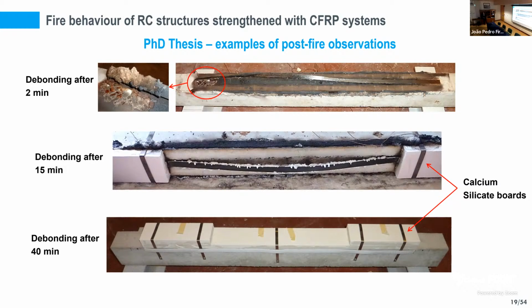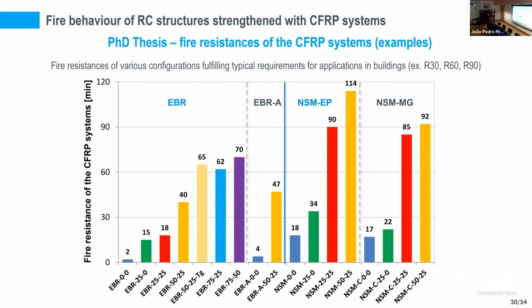Again, not enough for typical building requirements, but combining these thicker insulation zones with thinner insulation applied at the central zones, we were then able to extend the fire resistance of the strengthening system, which was our goal initially. And well, this plot with a lot of numbers summarizes the fire resistance times that we were able to achieve. The numbers above these bars show that we exceeded the typical fire resistance times required for buildings, which can be defined as 30 minutes, 60 minutes, and 90 minutes typically. So with the different configurations of fire protection and materials that we tested, we were able to find a solution for that problem that I described before.